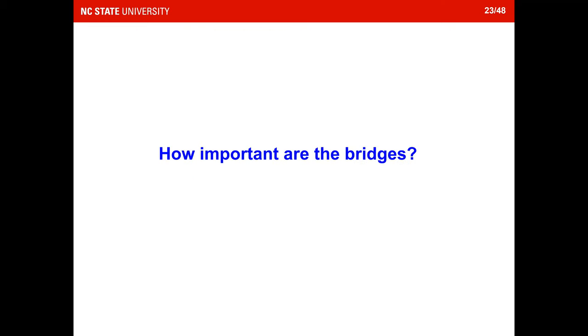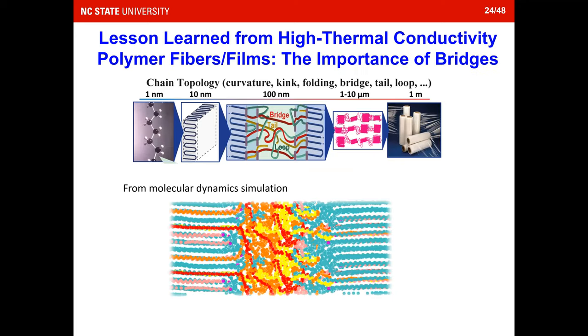We're trying to ask the student to understand how important those bridges are. It's very difficult to directly simulate this composite, but can we find some simple system, a simple model, to understand how important the bridges are to thermal transport? So we found one simple system is polymer fibers or polymer films after stretching. There is a lot of experimental data demonstrating that if you stretch a fiber or a film, you will have high thermal conductivity.